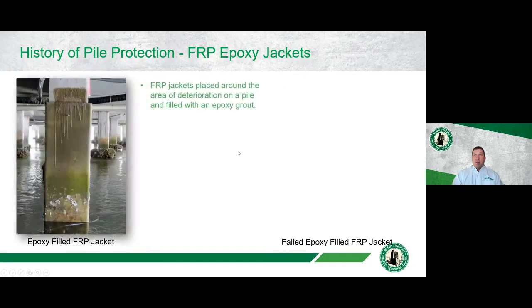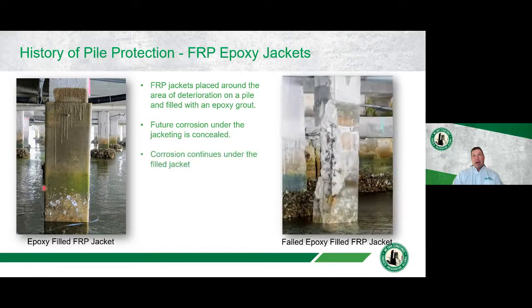Another type of jacket system that was also used to try to control the corrosion in these piles was an epoxy-filled fiberglass jacket as well. And essentially it works very, very similar. You take a fiberglass form, you place it around your concrete pile here, and you fill it with epoxy grout. And this is actually a recent picture that I just took a few months ago.